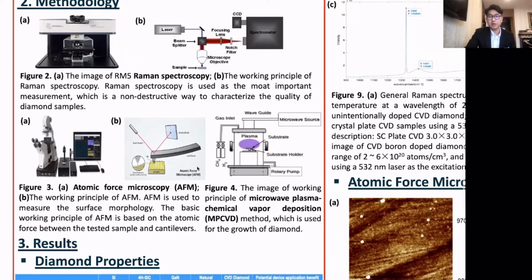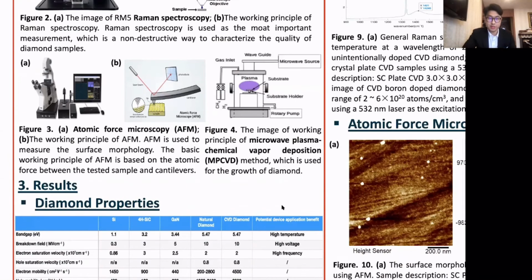For the preparation of diamonds, we choose to use the microwave plasma chemical vapor deposition method, MPCVD. According to research, it is the most efficient way to grow diamonds. And for the CVD growth method, it needs a growth condition with atomic hydrogen, a gaseous source of carbon in plasma with a gas temperature about 2000 degrees. In this process, we use methane and hydrogen to produce the high-quality films. The plasma is generated by the high frequency and high power microwave, which are responsible for the growth on the substrate. By using the methodology and the measurements, I got the following results.